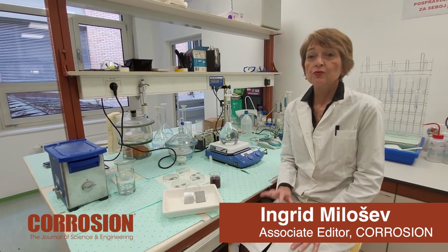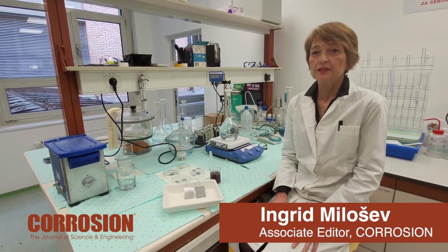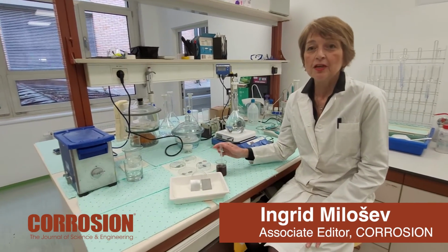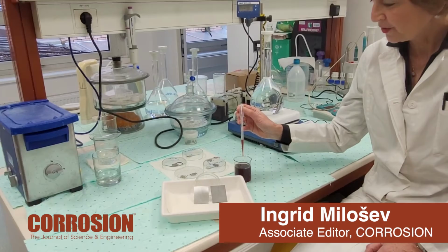Selected coatings showed good corrosion resistance during 50 days of immersion in chloride solution and were ultra-hydrophobic with beneficial properties such as self-cleaning. Namely, when immersed in slurry, the coatings remain clean. I will demonstrate this with similar super hydrophobic coatings.